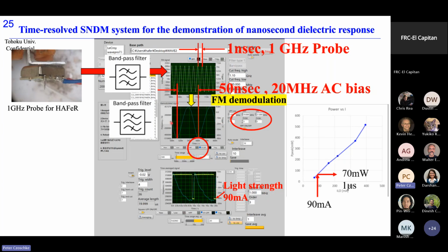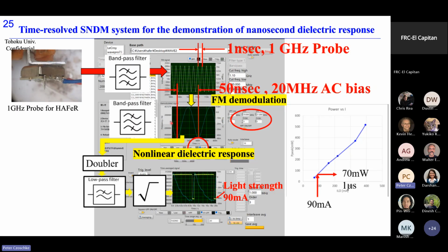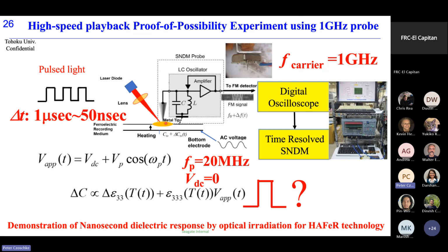But actually, we have to detect the envelope of this nonlinear dielectric response. So using a doubler and low pass filter and taking a square root, we obtain the envelope of the nonlinear dielectric response. Anyway, this is surely a signal from optical heating. Then, using this system, we conducted the high-speed proof of possibility experiment varying the light pulse duration from 1 microsecond to 50 nanoseconds.